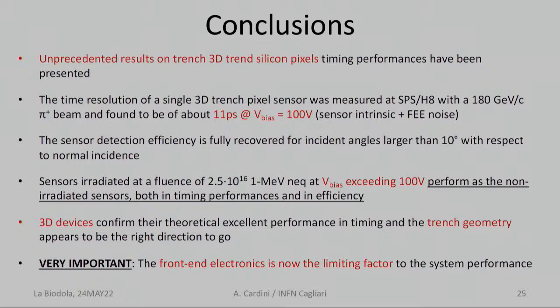So I come to my conclusion. I think I've shown you incredible results on the performance of these pixels. They have excellent time resolution, and they have the efficiency you need to operate them in a normal tracking environment. They perform very well up to 2.5 times 10 to the 16 with a slight increase in bias voltage, but still maintaining the timing performance. So those 3D devices confirm their theoretical excellent performance in timing for this particular geometry of 3D pixel, the trench geometry.